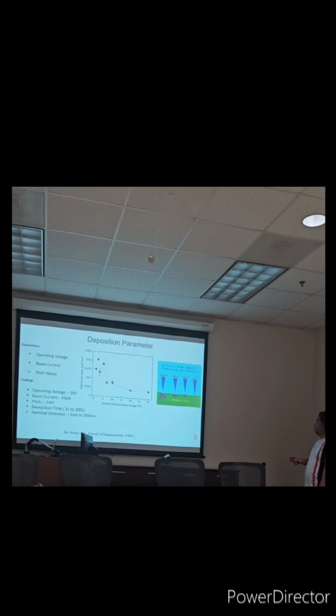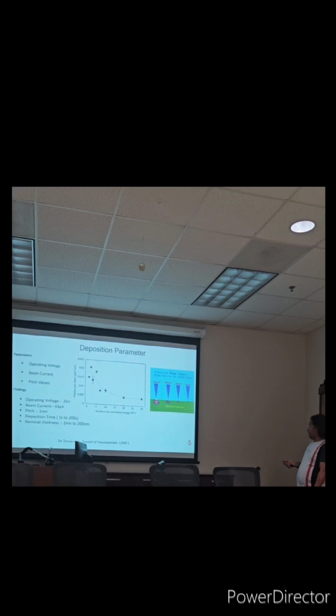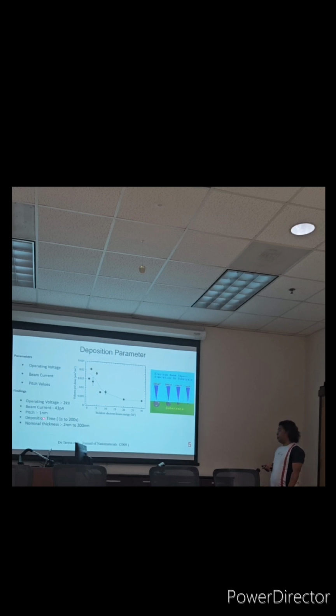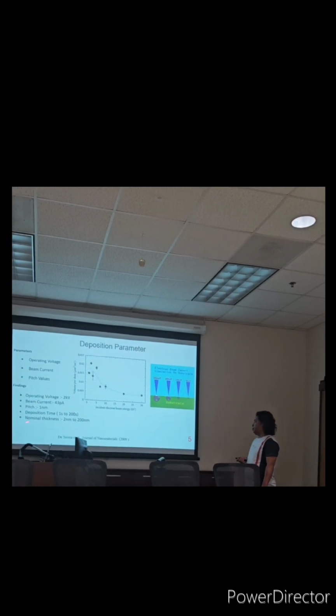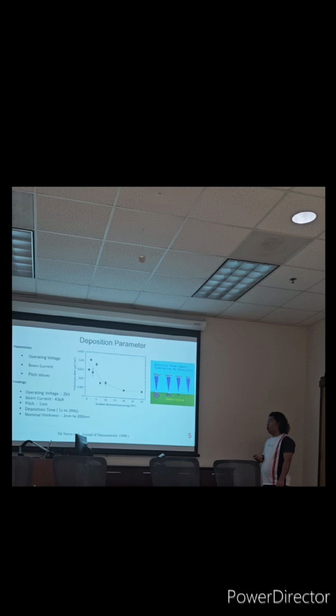The incoming electron beam with high operating voltage penetrates the substrate deeper, reducing the contribution from backscattered electrons and secondary electrons to the deposition process. This understanding led us to choose operating parameters: operating voltage 2 kilovolt, beam current 23 picoampere, pitch value 1 nanometer, which will be discussed further. And the deposition time to deposit a nominal thickness wire of 2 nanometer to 200 nanometer of 1 micrometer length requires 1 second to 200 seconds.